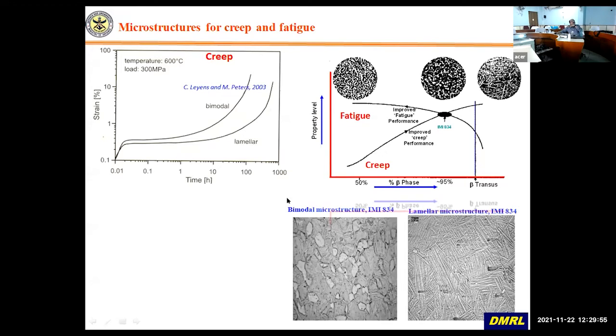But as far as fatigue is concerned, you can see here we are plotting fatigue curve, and this is a property value, just hypothetical curves, and this is a beta transus line. So as you cross the beta transus, you get a lamellar structure. So the creep properties are improving as you go towards the lamellar structure, whereas fatigue property deteriorates as you cross this. So fatigue property is much better if you have a bimodal kind of structure.